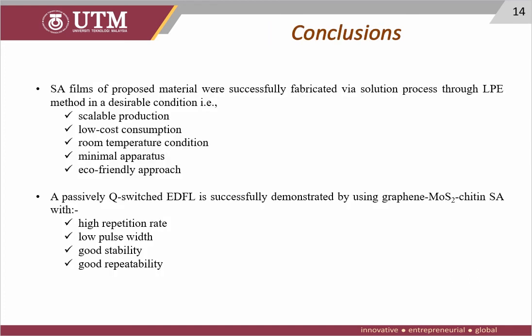As a conclusion, SA films of the proposed material, which is Graphene-MoS2 chitin, were successfully fabricated by the liquid phase exfoliation method under desirable conditions such as scalable production, low cost consumption, room temperature condition, minimal apparatus, and an eco-friendly approach with chitin as the biopolymer. And lastly, a passively Q-switched EDFL is successfully demonstrated using this SA with high repetition rate, low pulse width, good stability, and good repeatability.